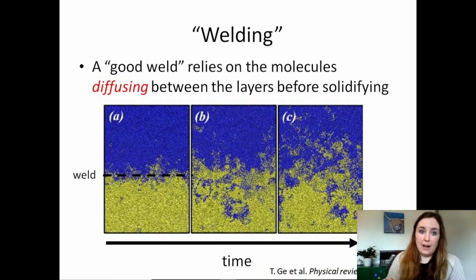In 3D printing, we don't have infinite time, unfortunately. Our time available for welding or for diffusion is determined by how fast your material cools down. As soon as your molten plastic cools down and solidifies, that completely arrests this interdiffusion process. So all welding will stop once your material is solid. But remember, we need it to cool down fairly quickly because we want to keep that structural integrity of the filament that we're laying down. So there's a very fine balance here about cooling down quickly enough to keep your structural integrity while allowing enough time for the welding to occur to form a good weld or a good bond between those layers.